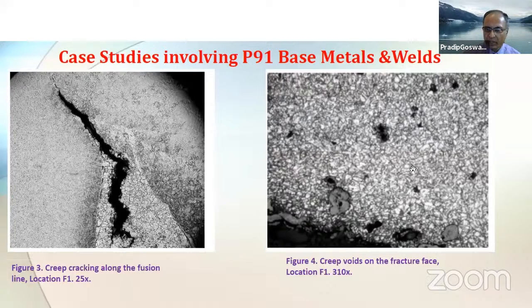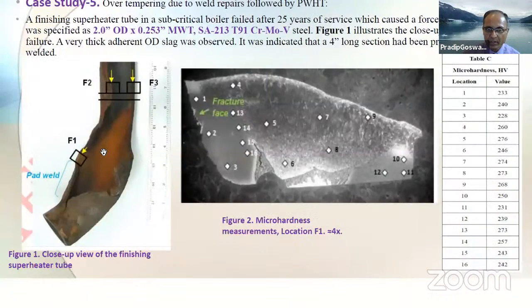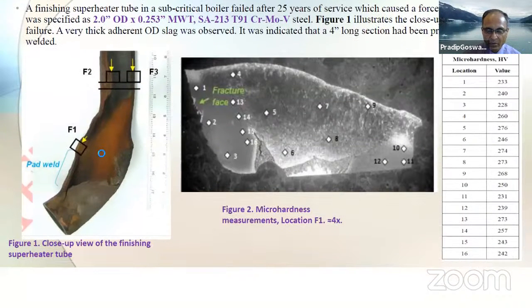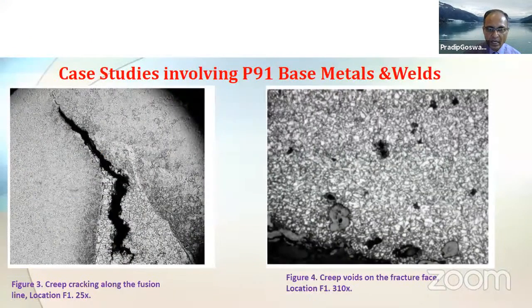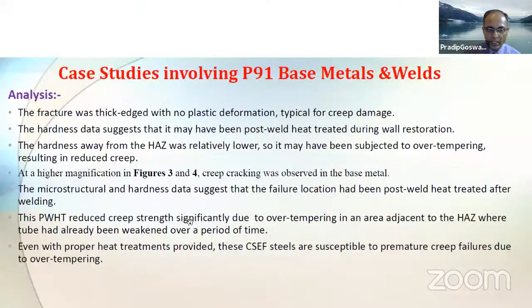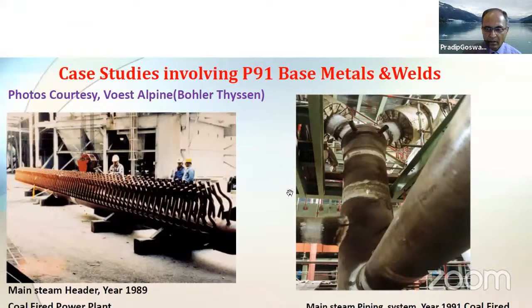That's an altogether different phenomenon, a different subject, but in a nutshell, this component failed due to a faulty welding practice, which is the pad weld, and it happened after prolonged exposure in the creep deformation temperature range. And subsequently, they decided to stop this pad weld or repair practice for this alloy in years to come. And I'm almost at the end of my presentation.